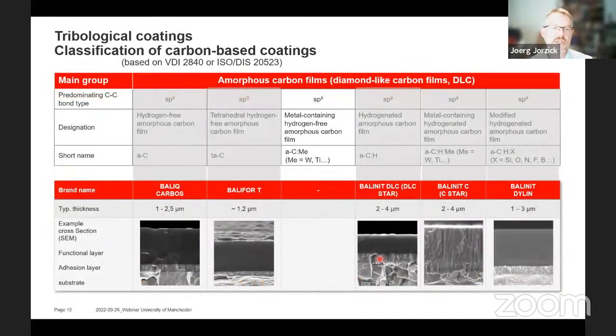We have some cross sections here where you see a little bit the difference. You see that most of the coatings are very smooth because they are applied with the PVD coating technology. The TAC coating, you see this structure here is slightly different, and that is because it has a different type of deposition method. Here we use a so-called arc evaporation process, where we have a high energetic arc evaporating the target material, and this leads to certain droplets in the surface which require some surface treatment after the coating, so that the coating can work in the respective application.